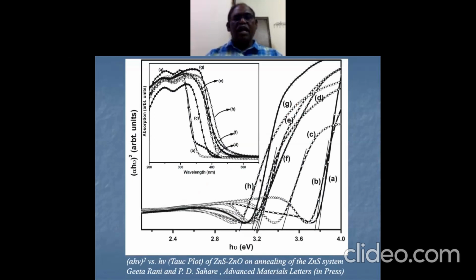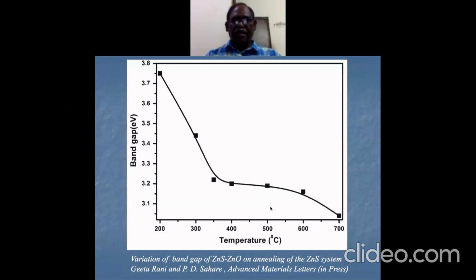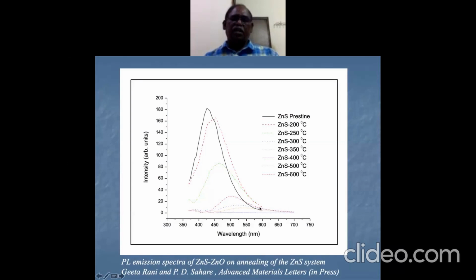And here that is what I was talking about. So this is the band gap of ZnO, and this is ZnS, and by changing the phase of one into another, you really can engineer the band gap of this material. And this shows how the band gap changes with temperature. And also when the band gap is changing, the defect levels change, because of the sulfur ions, or because it's not completely stoichiometric, that ZnO, even ZnS. So by changing that, this green peak in ZnS or ZnO also shifts. So there is a great, bigger blue shift that we also found in this.